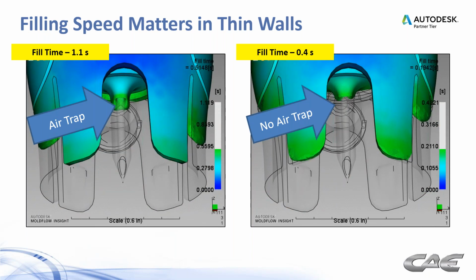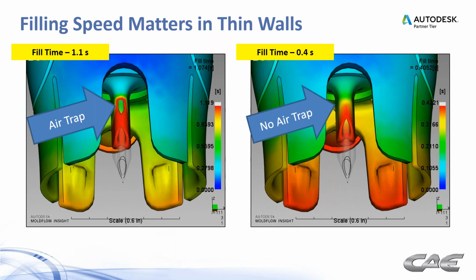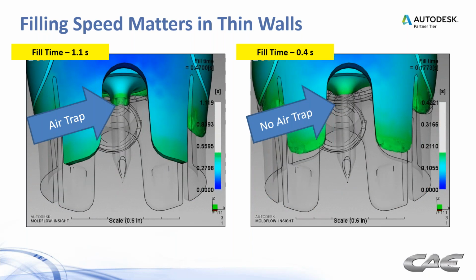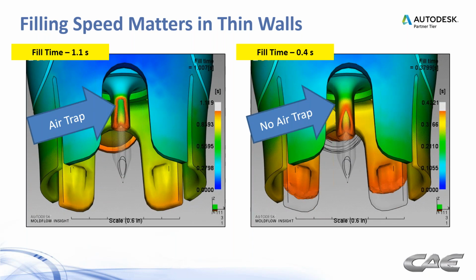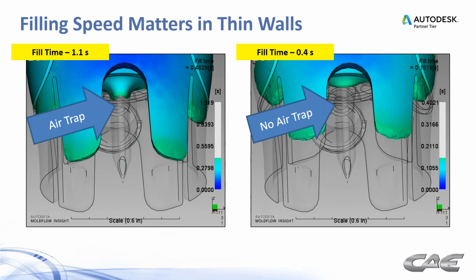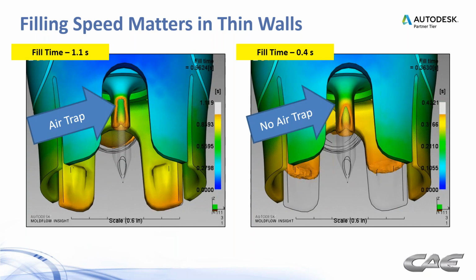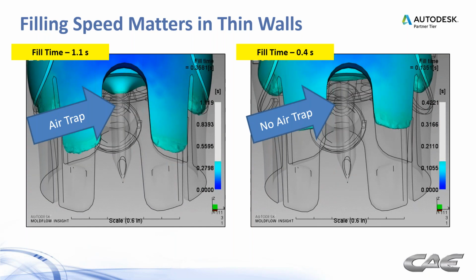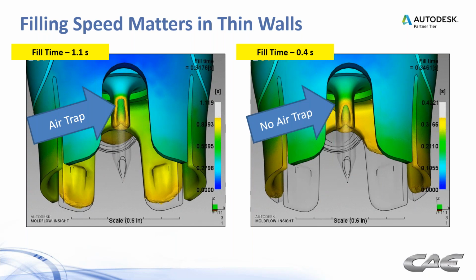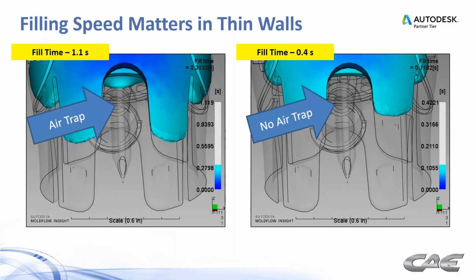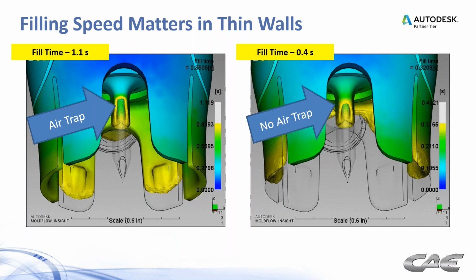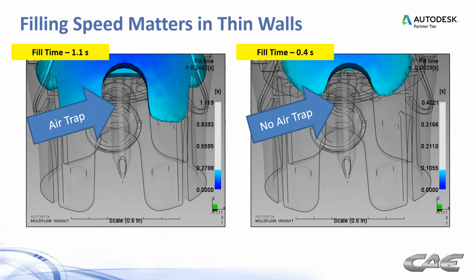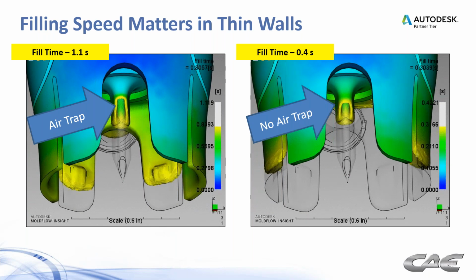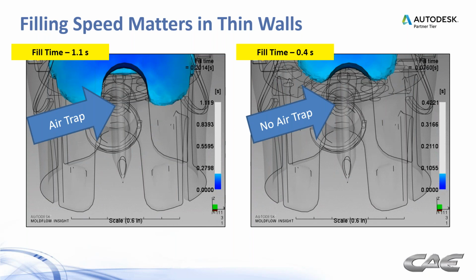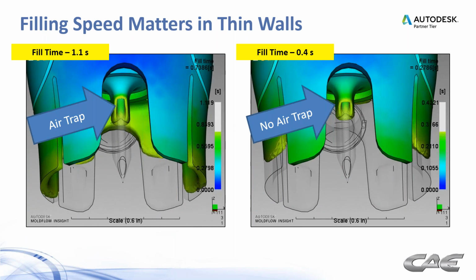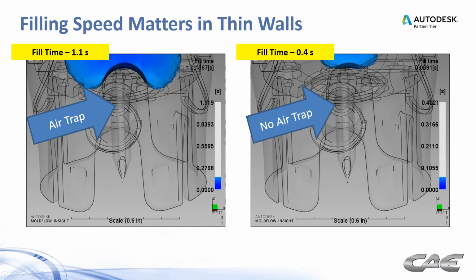So one of the solutions to doing that is looking at your fill speeds. And you can see with a quicker fill speed on the right, we were able to help mitigate that a little bit. But ultimately, a better choice would have been a thicker design. We're here to talk about how to make things thinner, but sometimes, for functionality's sake, you have to find out where you can draw the line. And in this case, a thicker cannula might have been a better solution. But oftentimes we can get through this by changing the process. And in this case, it was a fill speed issue.